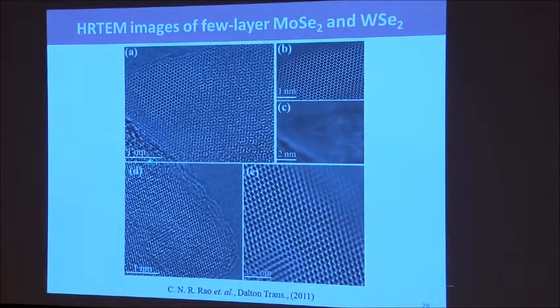Here is a bunch of very nice pictures: molybdenum selenide and tungsten selenide. You can see in molybdenum selenide that a single layer is there, and in this region there are 2 layers. You can actually do a transformation and see what is what.